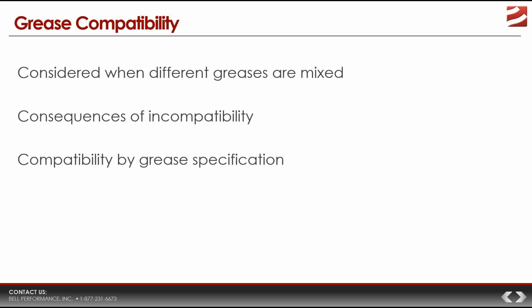So you want dropping point, mechanical stability, and worked penetration. If you've got two greases, you want those three specifications to be as similar as possible. If you have that, you should not have compatibility issues. In situations where it's absolutely critical to be on the right side of this issue, typically a customer won't do it by trial and error. They will contact the grease manufacturer, and the grease manufacturer will do bench testing of the specific greases in question to confirm those points.